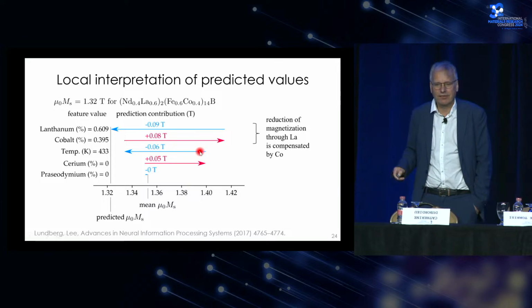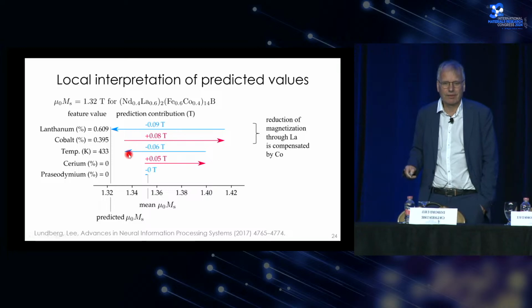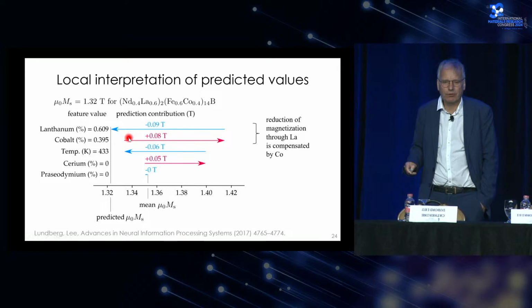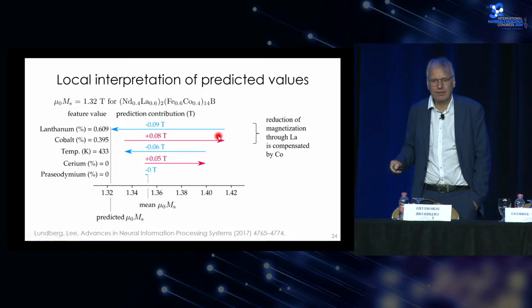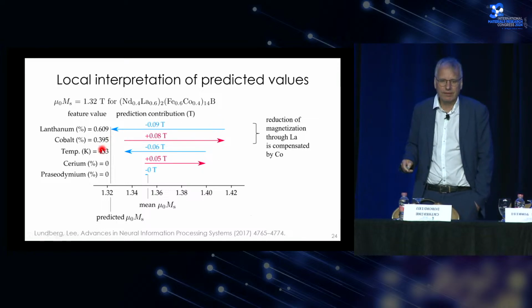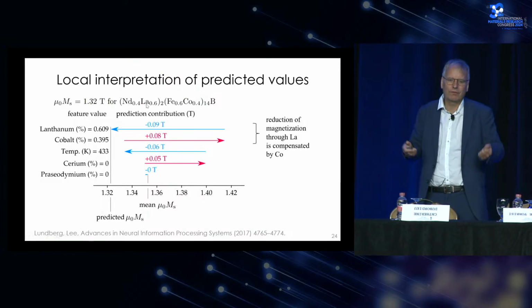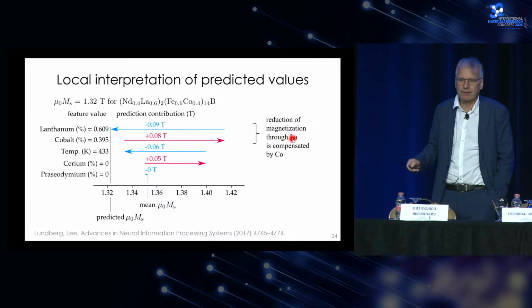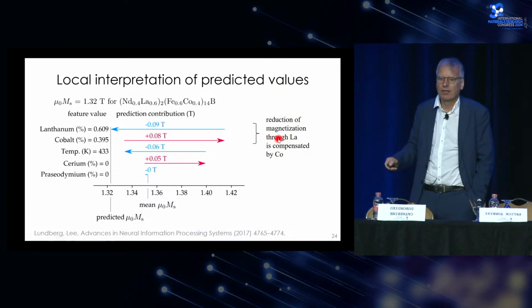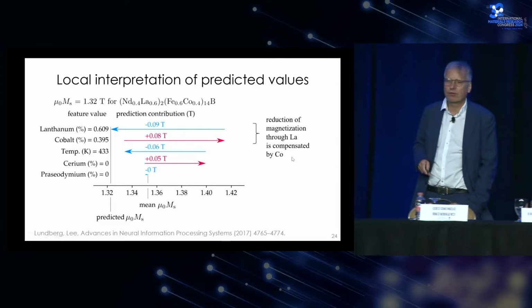We are at a higher temperature. We predict at 433 Kelvin. Because we are at elevated temperature, we reduce the magnetization. Because we have a certain amount of cobalt, we increase the magnetization. And because we have lanthanum instead of neodymium, we decrease the magnetization and arrive at our predicted value. What we learn from this analysis of the local contribution of the individual elements is that the reduction of magnetization by lanthanum can be compensated with the cobalt content.